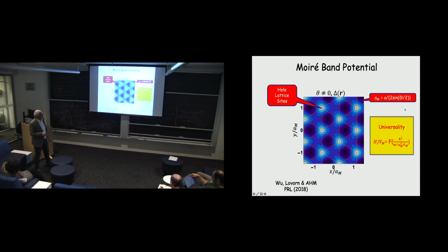And so it turns out that when you put in symmetry, this periodic potential only depends on two parameters: the strength of the potential and where the potential has its extrema, maxima or minima, and that's more or less fixed. It's the same for all these materials. As I was saying, the potential is greatest when the electron is sitting on a negative ion, and so all of these systems are the same.